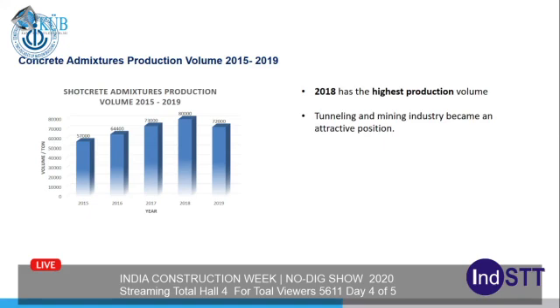And after that, last year it decreased from 80 to 72,000 tons. But when we compare with the plasticizer groups, we cannot say that this decreased similar to the water reducer groups. This actually decreased just a little bit when we compare with the previous groups. So again, we can say 2018 has the highest production volume for shotcrete admixtures.